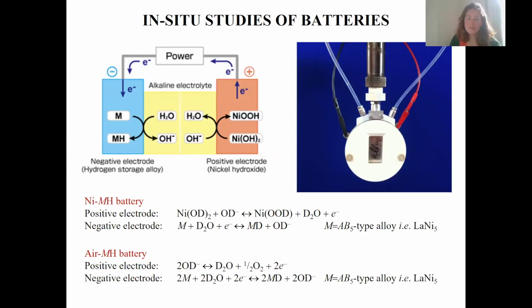I wonder, as a follow-up to that, does the beam affect the structure of the electrolyte at all? It shouldn't do. Our interaction with solids is particularly weak, and we are very low energy, especially when compared to X-rays. So we are very good at looking at battery materials, electrodes or electrolytes that suffer from beam damage under X-ray sources. If your material is damaged even on a laboratory X-ray, it's very unlikely to be damaged by neutrons.